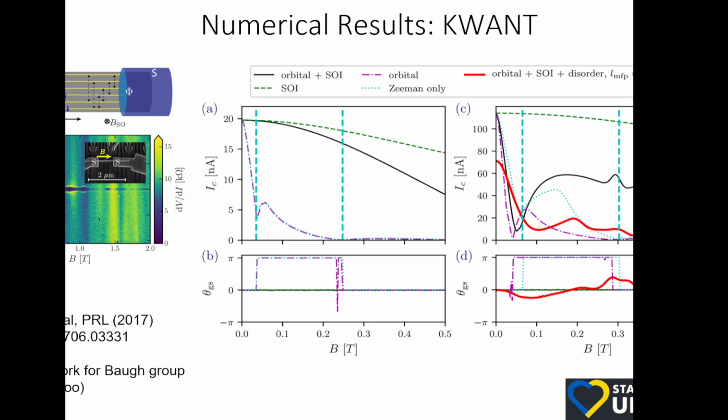Yeah, but these transverse modes are quantization in a cross-section of the nanowire, right? And by the way, the cross-section is hexagonal, it's not a cylinder. And you could implement it in Kwant. You could define the tight binding model with a hexagonal cross-section. And so if you solve the Schrodinger equation in just a cross-section, you will get some modes. And the idea is that in these nanowires, only a few of these levels are occupied. So in a metal, every atom carries a mode.